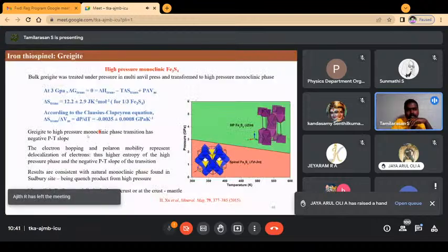And we went on to study the high pressure behavior, and then we plotted the PT curve, which shows how the transition pressure changes with respect to temperature. Here it is a negative slope, which means the higher the temperature, the transition from cubic to monoclinic is going to happen at a lower pressure than at room temperature, which is 3 GPa. It's going to be at much lower pressure at higher temperature.